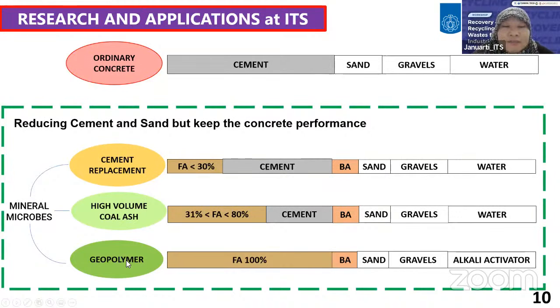Here, there are three methods to make concrete by using fly ash and bottom ash. As a cement replacement, usually we use fly ash at a maximum of 30% to replace cement. And we also use bottom ash to replace sand, and we also use gravel and water. And the second method, if the quality of fly ash is very good, then we can replace cement at a maximum of 80%. So this is very good because the price is reduced also. We can have a cheaper concrete, but here maybe the mechanical strength also reduces.